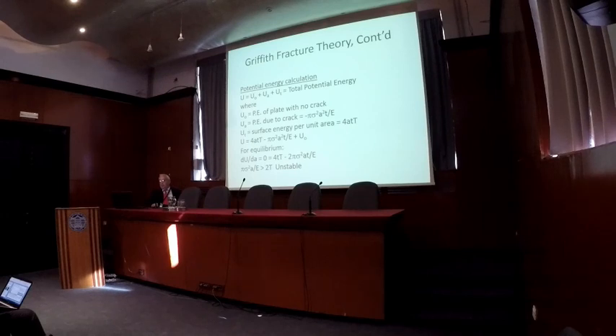So for equilibrium, we use a mechanics concept that I only teach in graduate courses, which is the energy approach. That is, you write the energy of a structure, and then you take the first derivative with respect to the variable and set that equal to zero, and that can give you an equilibrium position. So when we did that, I get this term down here, and that was sort of the Griffith energy. If you take a second derivative and it's negative, you get unstable. If it's positive, you get stable. But in this case, the variable is crack length a, which is a half crack length in his geometry, and when you take the second derivative, you get a negative term here. So it means that's an unstable position. Once you reach that equilibrium, it's unstable and you can get failure.